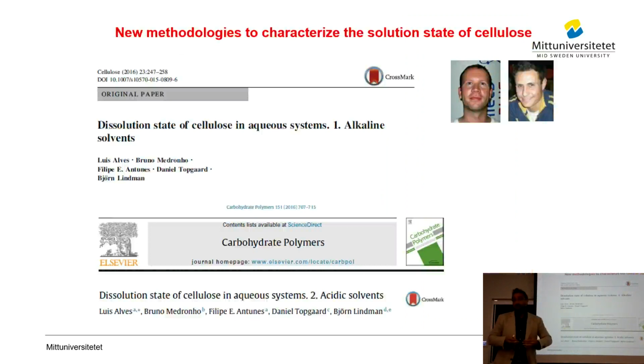Of course, at the time we were also interested in the fundamentals, and it's always tricky to say how well dissolved the solution is. I mean, I can look with the naked eye, it's transparent, I say it's dissolved. But if I put it under an optical microscope, I might see some particles there. So it's dissolved, but how well dissolved is it? If I go to submicron, I still might see some aggregates, colloidal aggregates. So it's always tricky to say that something is dissolved or not.